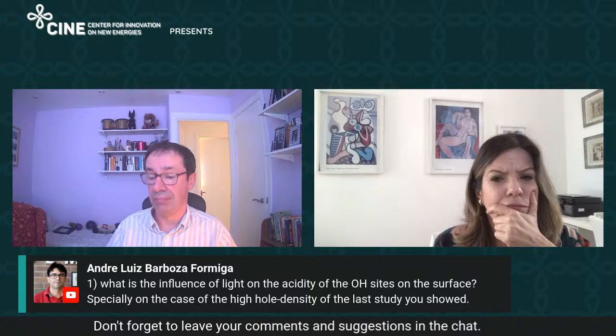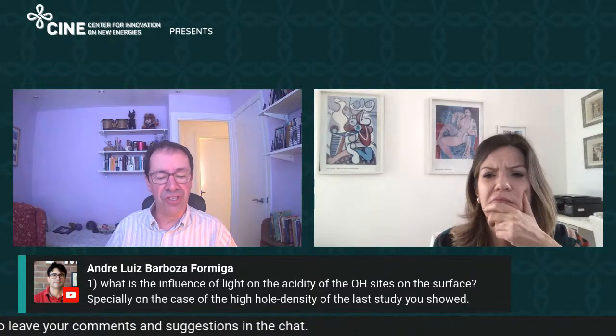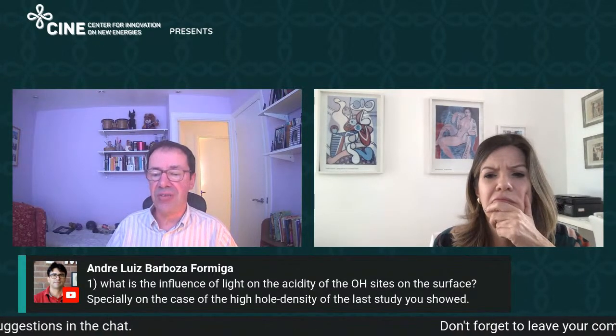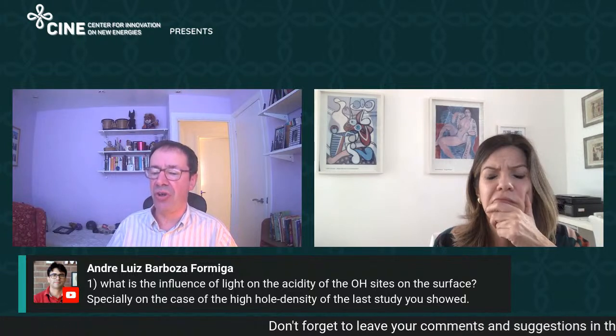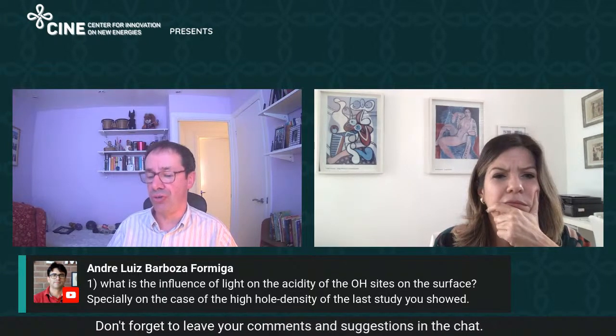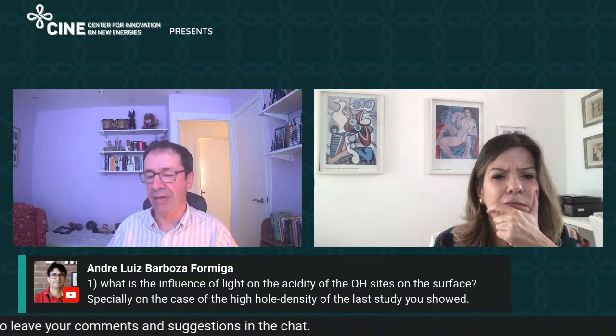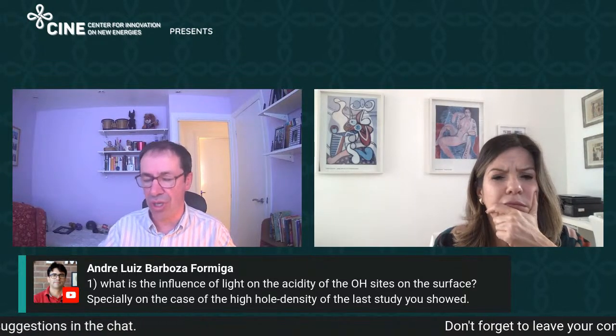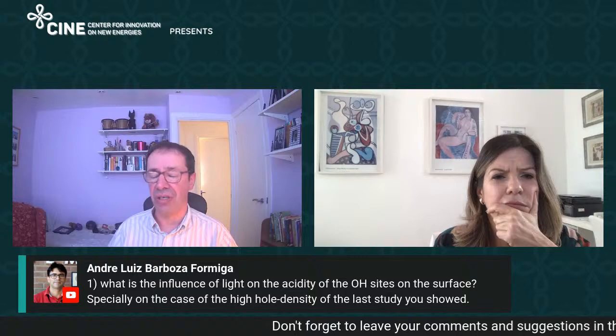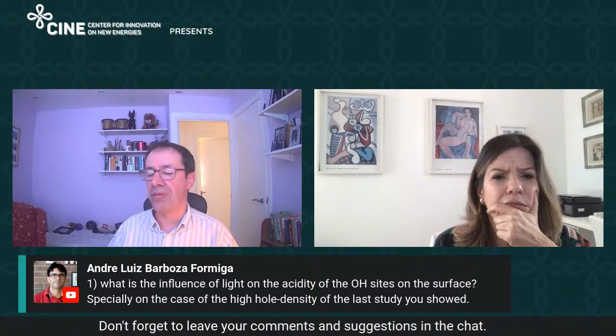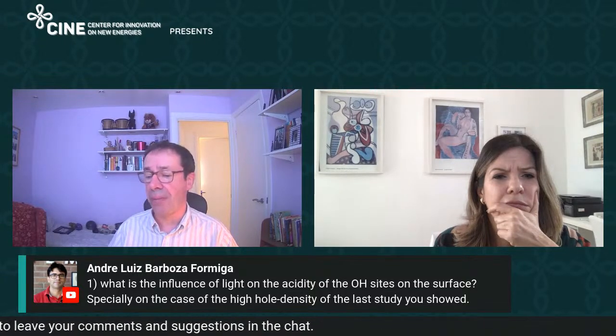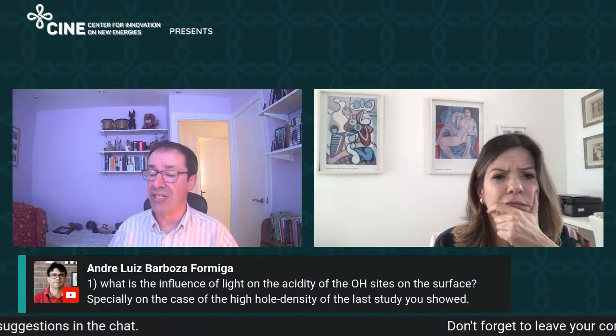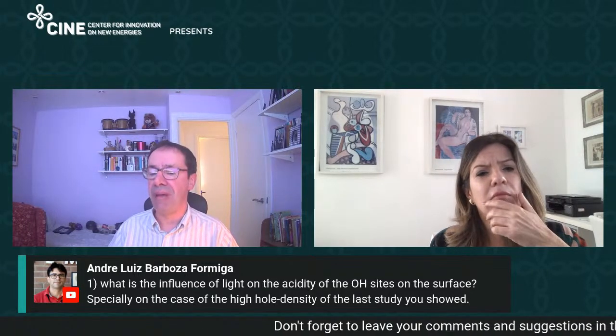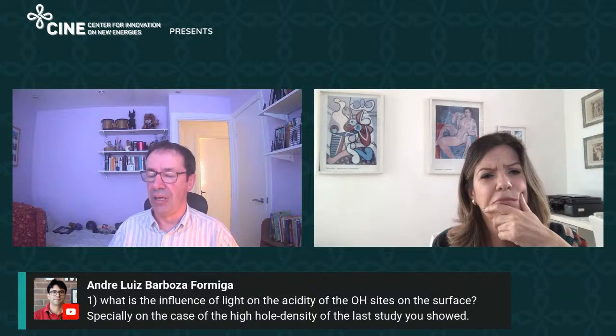But at the same time, there's quite a lot of indication that as you accumulate holes on the surface, there's proton release. And so one of the suggestions from the modeling by Victor Batista is that actually hole accumulation on the surface of hematite is charge neutral, which is why you're able to bring three holes together to oxidize water without having an activation barrier for the reaction, which essentially is the same idea as in plants, that the manganese cluster drives proton-coupled electron transfer, so that each oxidation releases a proton, and the cluster remains charge neutral on the surface during water oxidation. I'm not sure that fully answered your question. That's probably the best I can do.